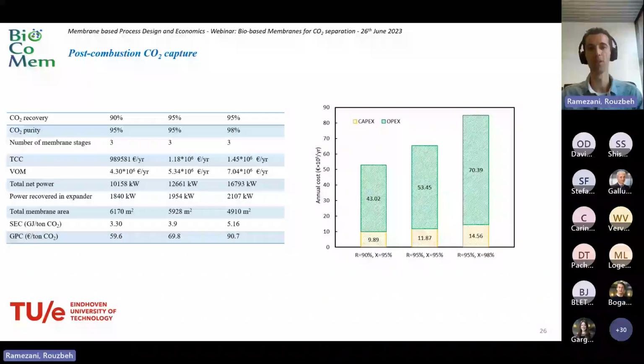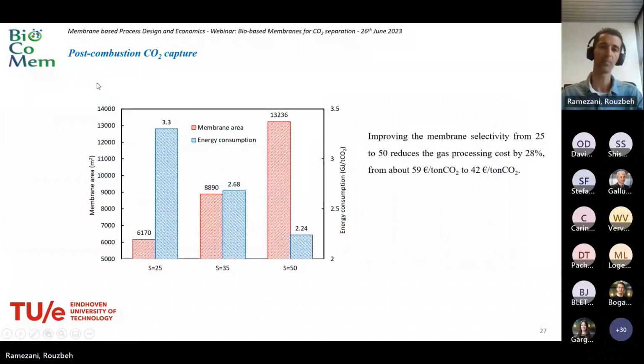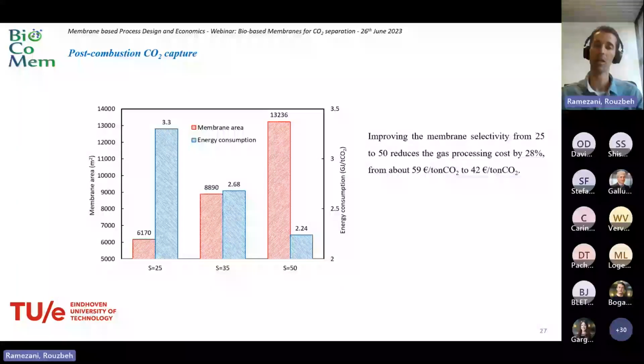But usually in post-combustion, we don't need that high a recovery of 95%. Based on the literature, if you are okay with 90% recovery, this application could be competitive with the literature. And the last one is the effect of selectivity. If all the properties are the same, and permeance is the same, the membrane selectivity for post-combustion is 25. Let's see what happens if we improve membrane selectivity to about 50. You can see the separation cost reduced about 28%, from 59 euro to about 42 euro.